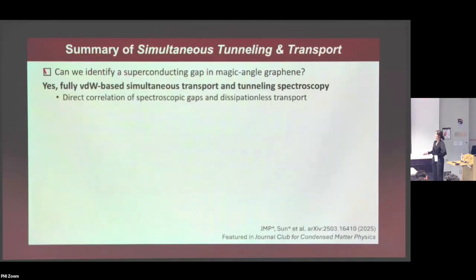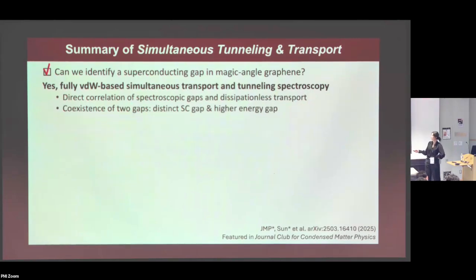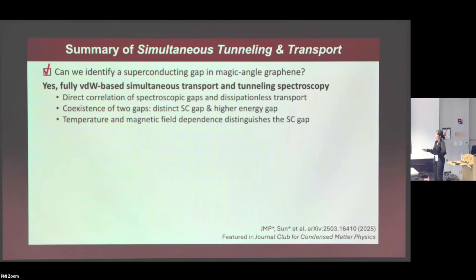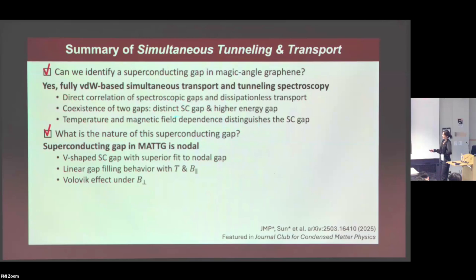Okay, so we can come back to the questions. Can you identify the superconducting gap? Yes, we could use fully van der Waals device-based measurements to do simultaneous measurements. We could directly correlate the gaps with the transport features, where we were able to distinguish the superconducting gap from other gaps and isolate that superconducting gap, and that superconducting gap seems to be pretty nodal.